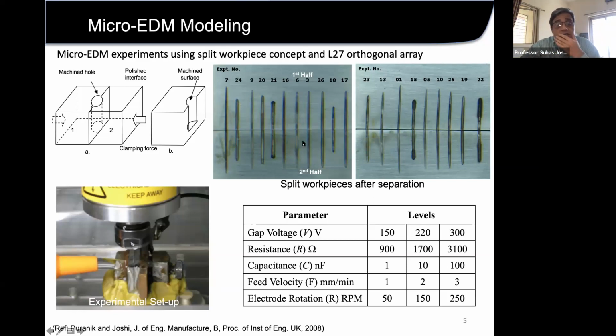So we did a lot of experiments, almost 20. This was according to that orthogonal array, about 27 experiments, and all of them, you can see that they are exactly at the center, so that the shape of one half is exactly equal to the shape of the other half. And we found that there is a huge length to diameter ratio. It is possible, about 10 is easily possible in the micro EDM process.